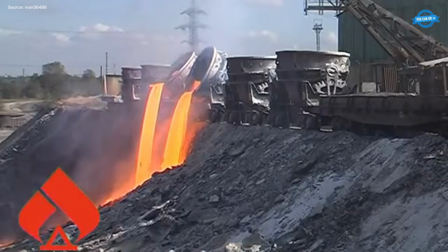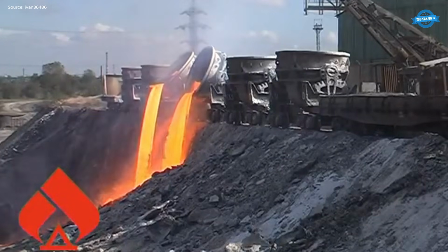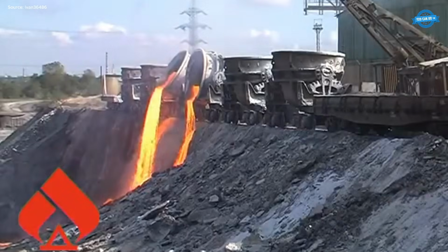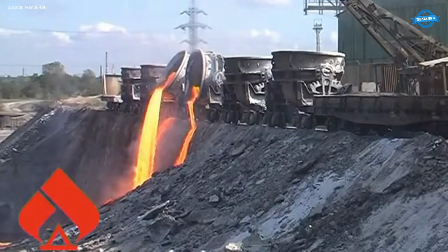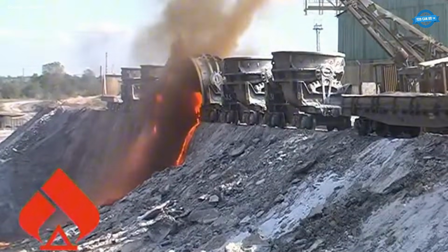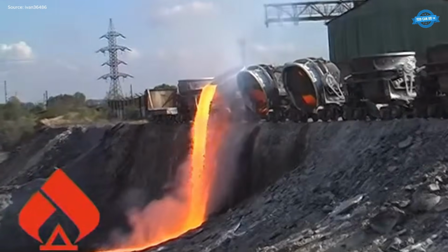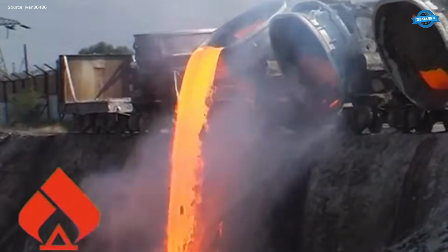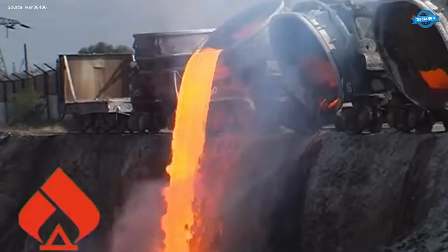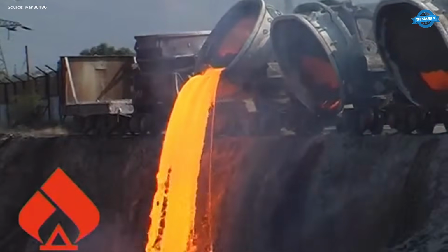These pots are designed with high-strength steel and feature thick refractory linings to withstand the extreme thermal and mechanical loads during repeated service cycles. Each pot must resist temperatures exceeding 1,600 degrees Celsius and is engineered for precise balance during tilting to ensure operator safety and structural integrity.